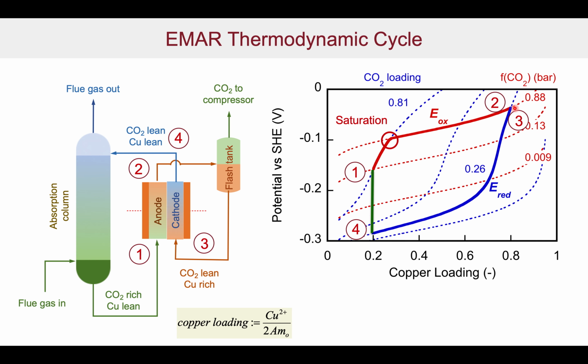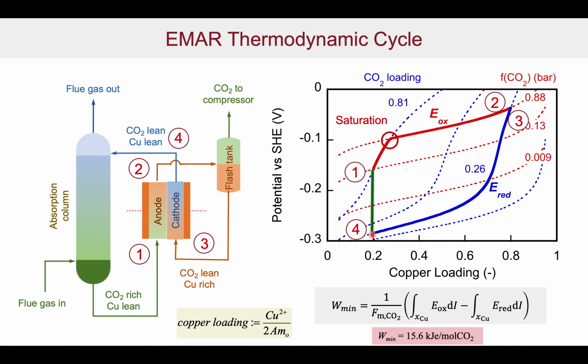So what we've got here is the relative concentration in equilibrium with the gas at that particular fugacity. And so we can see this line follows a constant concentration curve. This, of course, is a thermodynamic line, and we can look at the overall cycle, and we can calculate the minimum amount of work that's required to do this separation, and it's basically around 15.6. So it's really just the integral of the potential over the current for the two legs of the oxidation and reduction cycles.